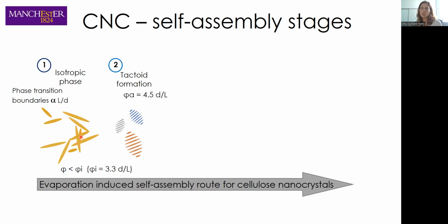But even in the isotropic phase, we know that agglomerations are taking place, because when you have two high aspect ratio particles in close proximity, and every now and again they come to that close proximity, they are bundling up. And in the first stage of critical volume concentration, which is again determined by their aspect ratio, we assume that the precursors of the crystal nucleation, if you will, are taking place.